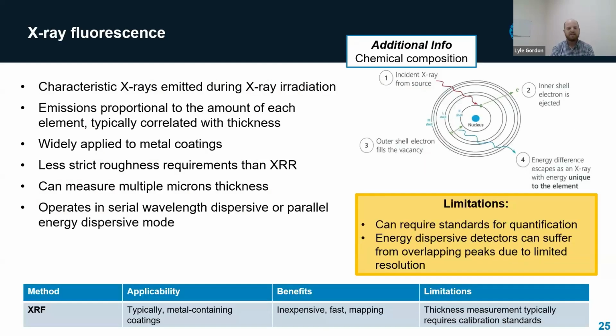So another technique that's really widely used for characterizing optically opaque films is X-ray fluorescence. And we'll show an application on the next slide where we combine the X-ray reflectivity and the X-ray fluorescence together for measurement of an opaque film. So in this case, we irradiate the sample with X-rays, and then the specific elements in the film, particularly metals and heavier elements, will emit characteristic X-rays. And we can detect those X-rays as we measure the sample, and the intensity of those, in some cases relative to the substrate, can tell you the thickness of the film.